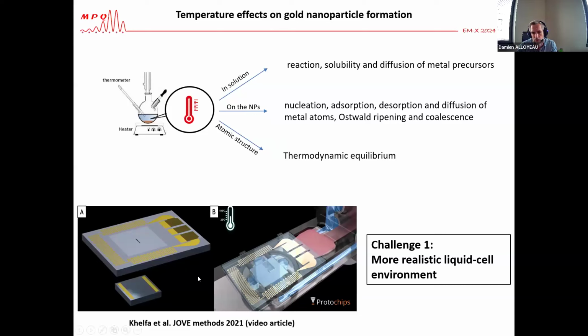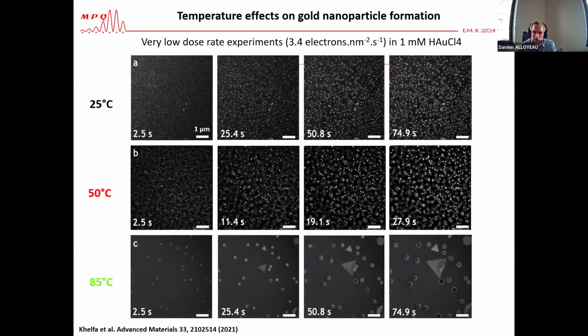And here we have used those recently developed temperature control liquid cells that have been developed by Protochips, in which you have a resistance that is embedded inside the silicon wafer that allows you to control the temperature of the whole liquid cell between 25 and 100 degrees. And if you want to know more about how those liquid cells work, please have a look at these video articles we did some years ago. And here I show you an example where we work in a very low dose experiment, and you observe the growth of gold nanoparticles at 25, 50, and 85 degrees. And you see that temperature has a drastic effect on the nucleation and growth process. So we try to quantify this.